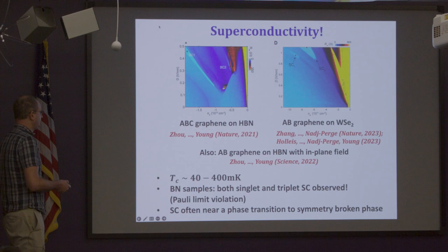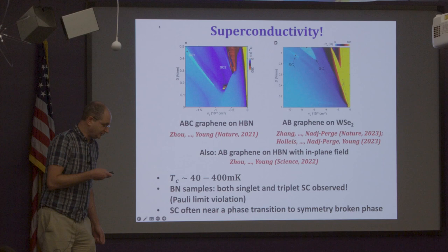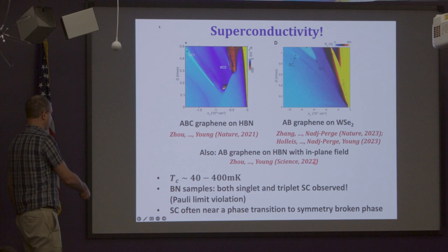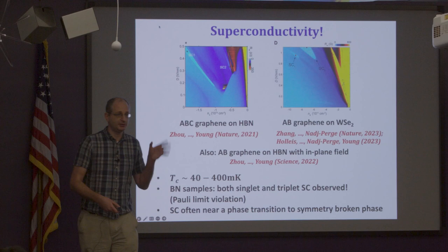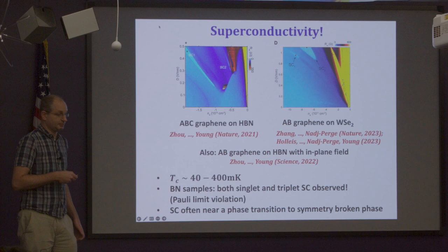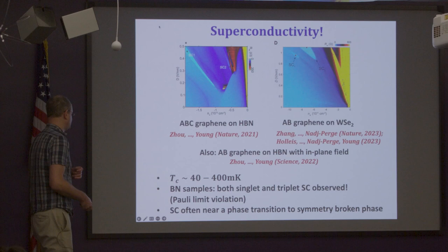Just a brief recap. We have these different superconducting states. Even within the same system, you can have different superconducting pockets, as you saw. Just learned about SC3, also lurking somewhere around here. What we saw is that, interestingly, in the trilayer you can have two superconducting regions within the same phase diagram. One is a spin singlet and the other one is spin triplet. Remember, here spin-orbit coupling is small, so it makes sense to distinguish them. They're not strongly mixed. And the system can choose, and it chooses triplet for the smaller one, for SC2, and singlet for the more robust one. There's a caveat on that I'll mention as we go along.